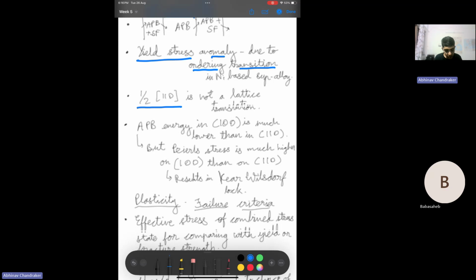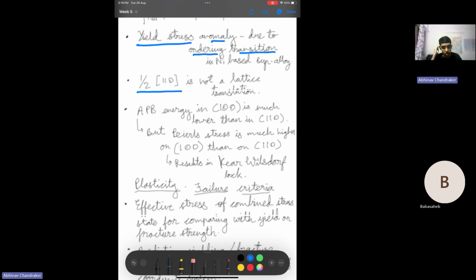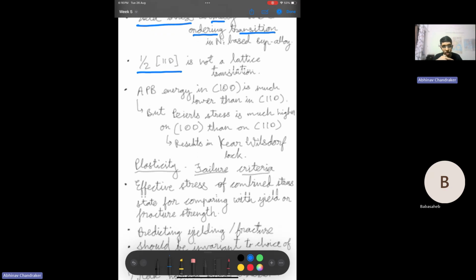And in these alloys, half 110, which is the lattice translation for FCC, will not be an actual lattice translation, because that will lead to a change in the neighborhood of the atoms of the elements, because AB might become AA afterwards. So there is a change. It's not a lattice translation.